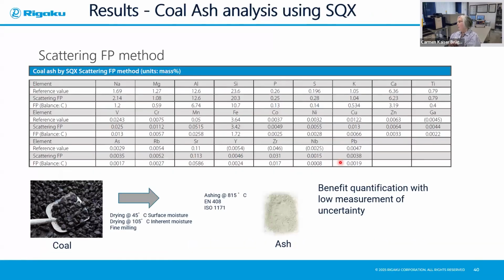Here's another example, but now we have a traditional coal sample. Of course we need to also measure coal, because the coal will be used in conjunction with the alternative fuels. We cannot use just alternative fuels in the kiln. It has to be accompanied with coal. Coal traditionally can be measured with a fusion method, but in this example I showed you how we can ash the coal by using an ISO standard, as you see here. And the ash content can then be measured for the trace elements that we have here.